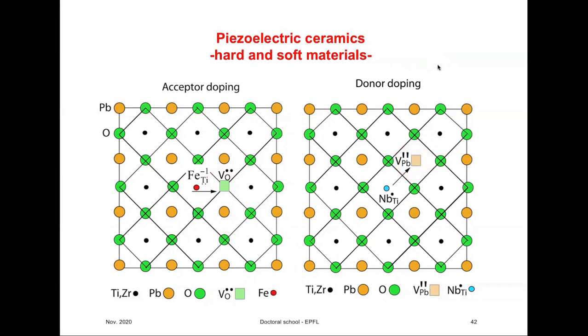Now, immediately we see one big difference, and that is that these oxygen vacancies see a network of oxygen octahedra along which they can move. Okay? While it is much more difficult for a big lead or lead vacancy to move in the structure. It's a longer distance, and there is no network as clearly defined as in the case of oxygen octahedra. So oxygen octahedra again play a role here.